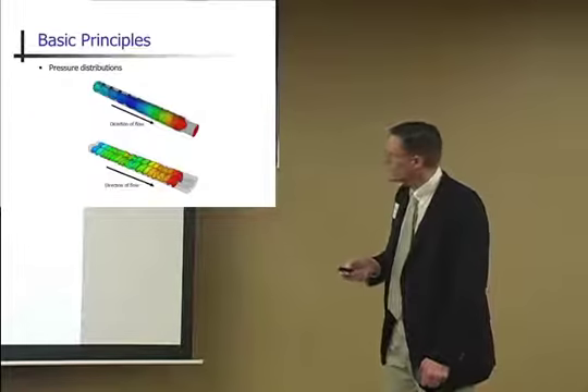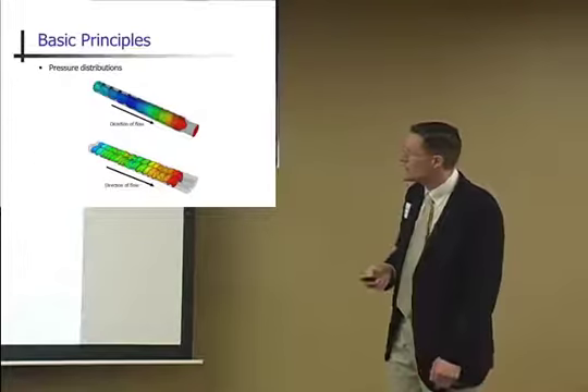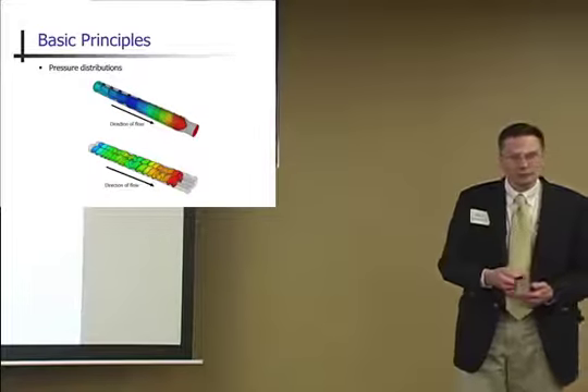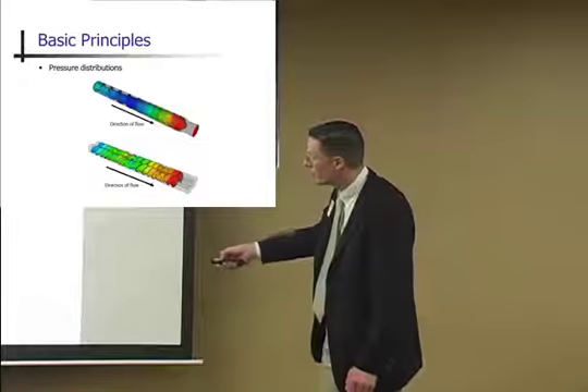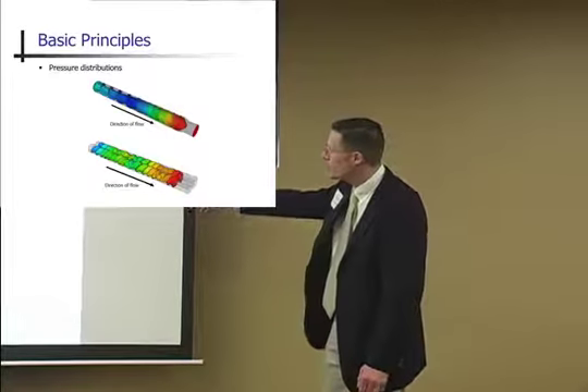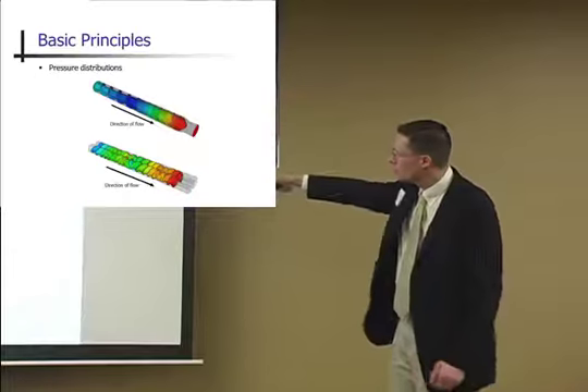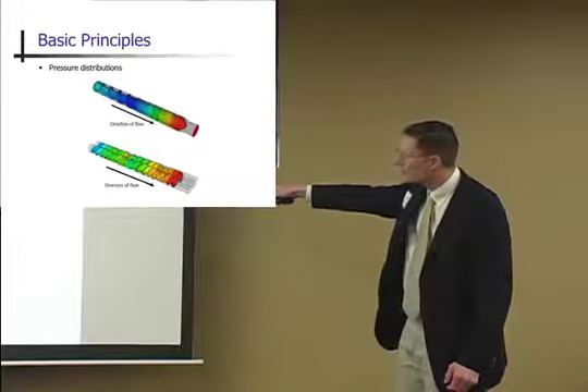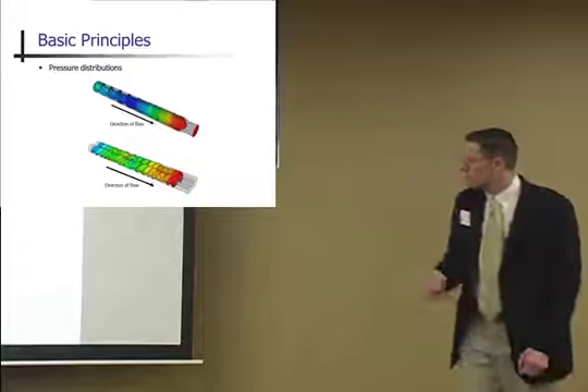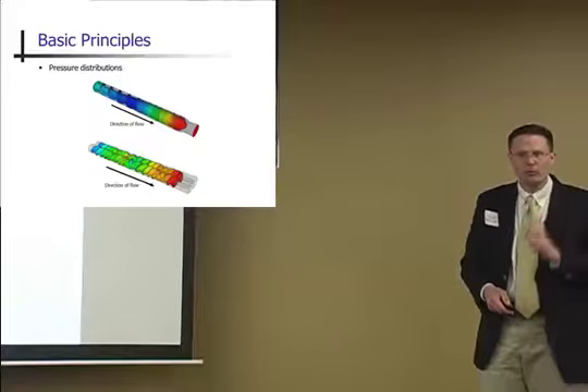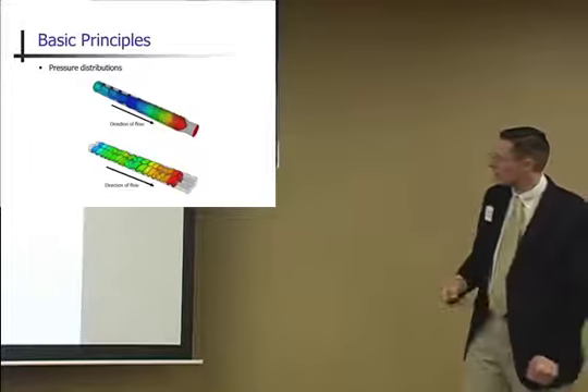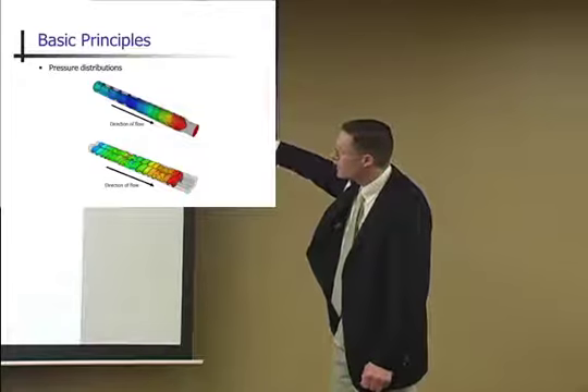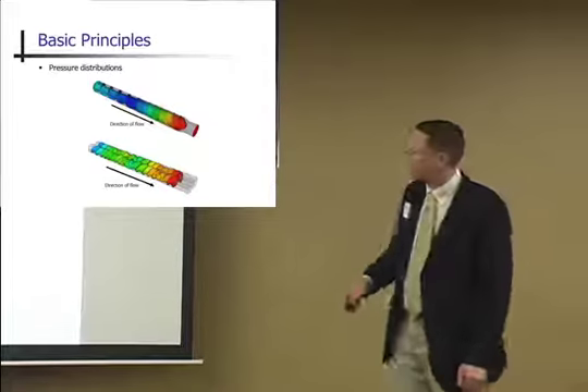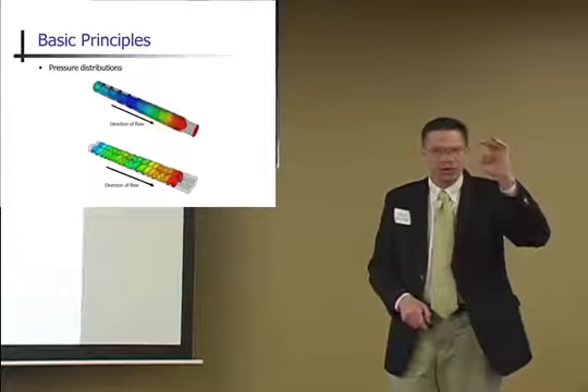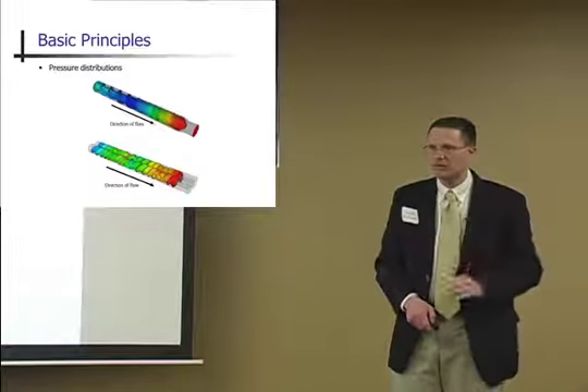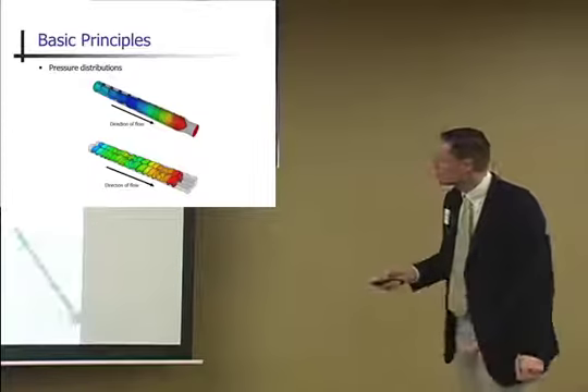In terms of extrusion, we're going to talk in the next little while about single screw or twin screw extruders. You either have a single conveyor or you have dual conveyors. Basically what happens is not just does the temperature increase, but the pressure increases the closer you get to the die. And same with the twin screw. Basically because you have a little die restriction, a little die hole where the pellets flow out of. And so if you have 10 pounds a minute or 20 pounds a minute flowing into your extruder, and you have one die opening that's 3 millimeters, you could have 20 pounds a minute coming out of that die opening. So the pressure increases.